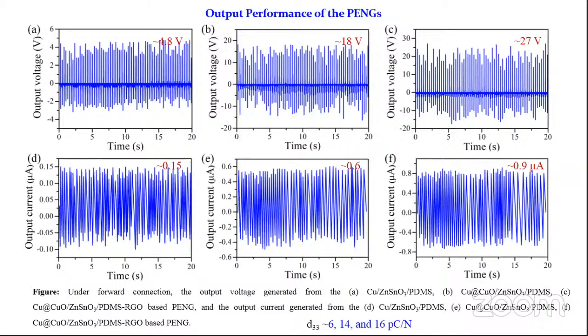So here we can see that a PN heterojunction can enhance the output performance of the fabricated PENG. What happens actually is that the zinc stannate nanoparticles contain a huge number of free electrons. Those free electrons diminish the piezo potential. When we use the copper oxide layer, which is a p-type material, that p-type material will combine with the free electrons, so the piezo potential is enhanced.